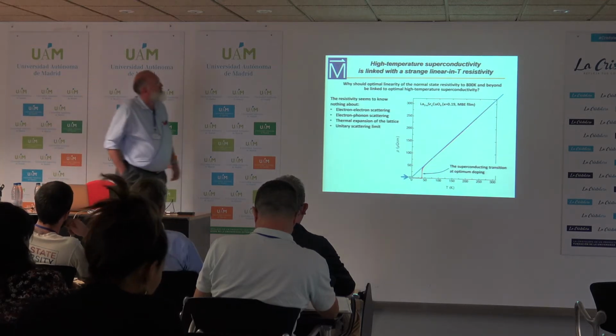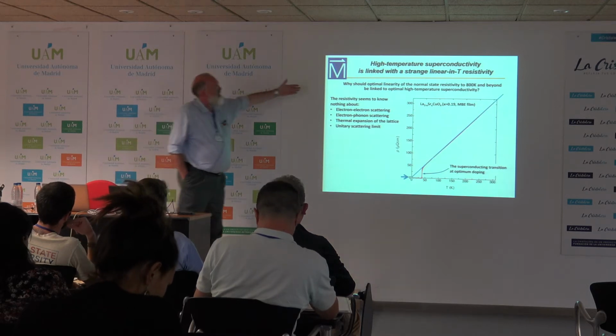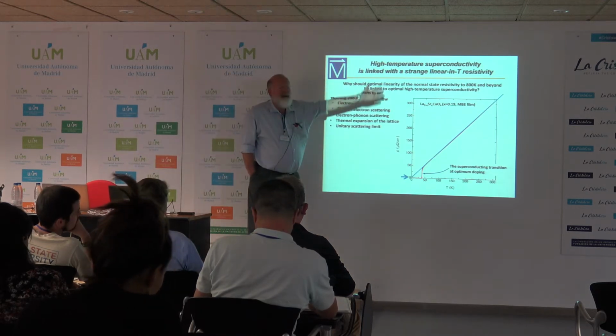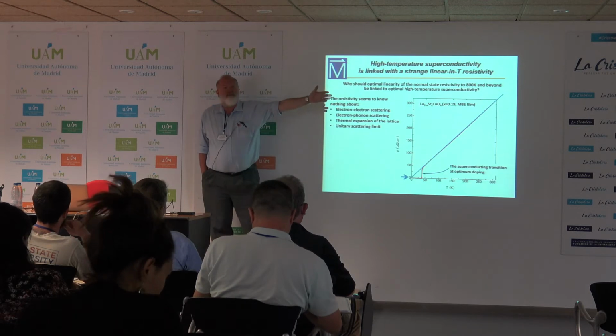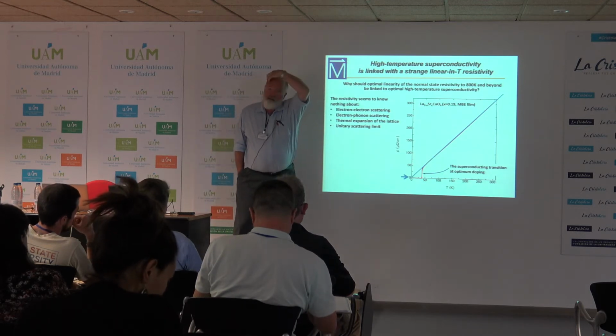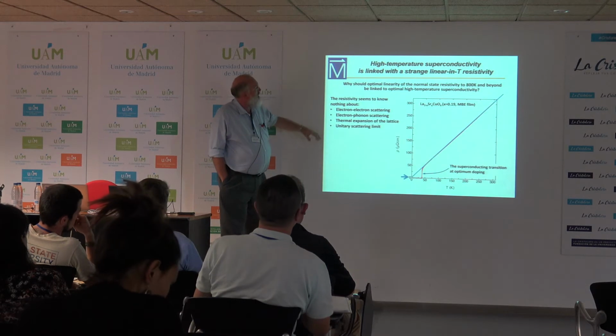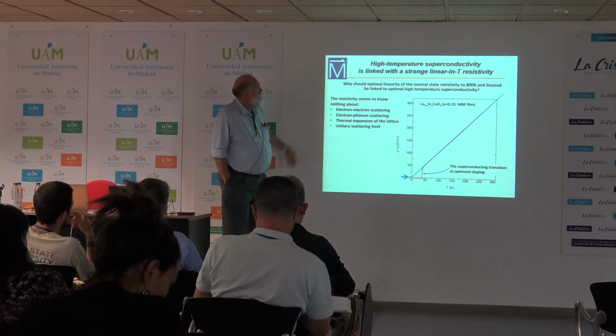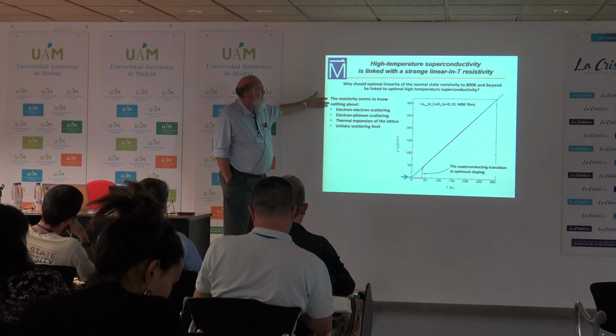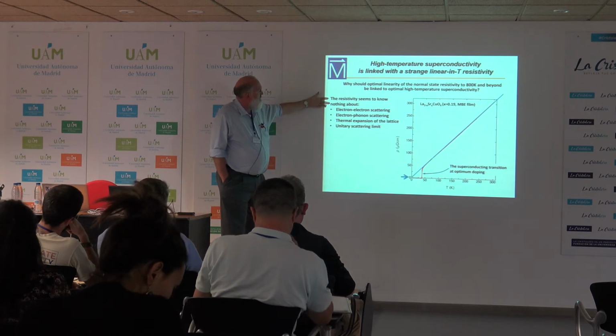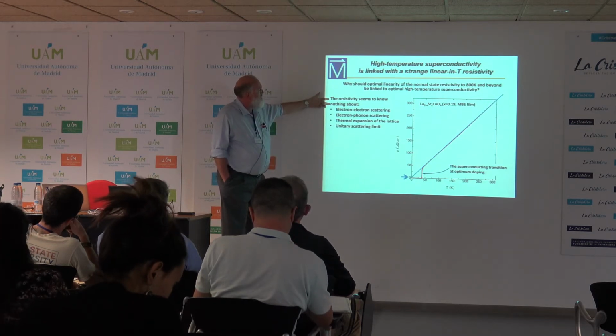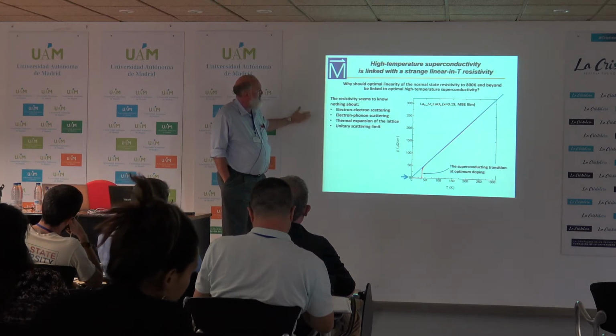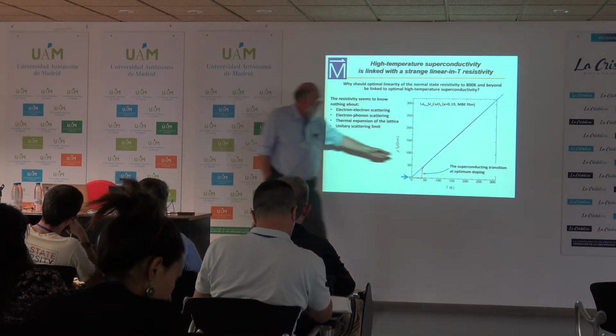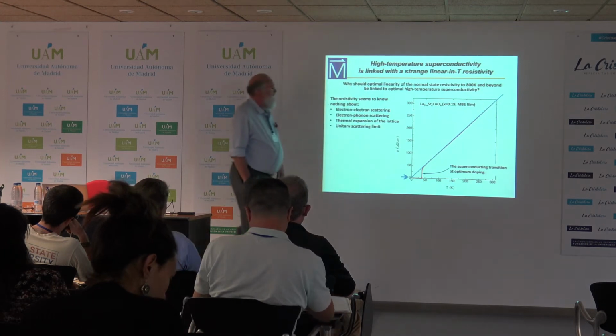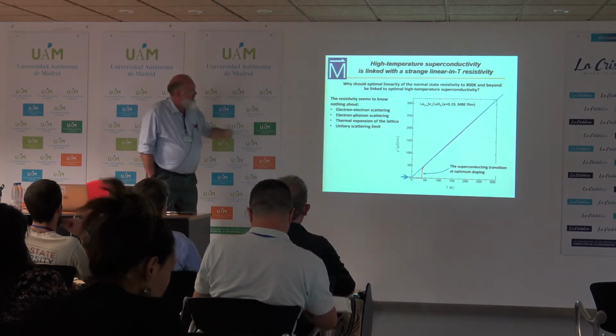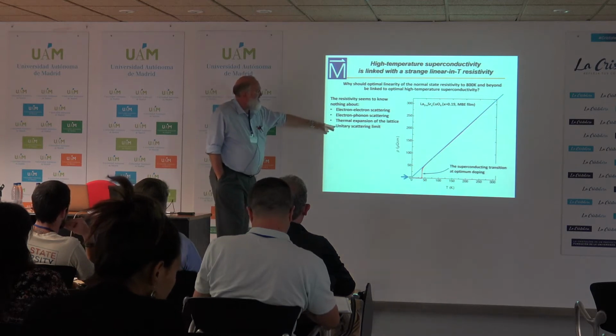Why should optimal linearity of the normal state resistivity extend to 800 Kelvin in the YBCO data from Sam Martin that Tony showed in his talk, all the way down to TC? It's not clear even to this day. But the resistivity, as Tony discussed, seems to know nothing about electron-electron scattering, which would go as T squared. Electron-phonon scattering would have a linear temperature behavior over some range, but then would deviate from it. Thermal expansion of the lattice doesn't seem to play a role.